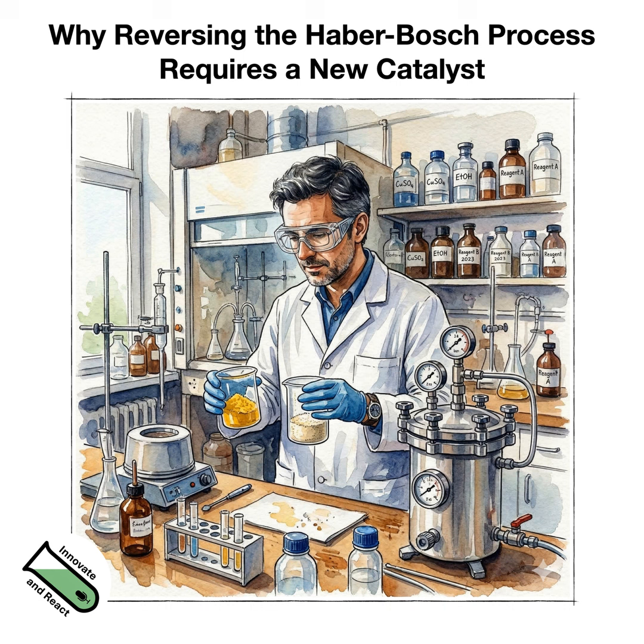So we get lower rates on iron nitride, and that was also one starting point for research that we did recently. That was looking at a way to prevent nitridation of iron by changing something in the catalyst. And it turned out that, for instance, alloying iron with another metal that is not a typical nitride forming metal, and we looked at cobalt in particular, indeed helps to prevent the bulk nitridation of the iron. So the surface iron is then surrounded by cobalt and not by nitrogen.